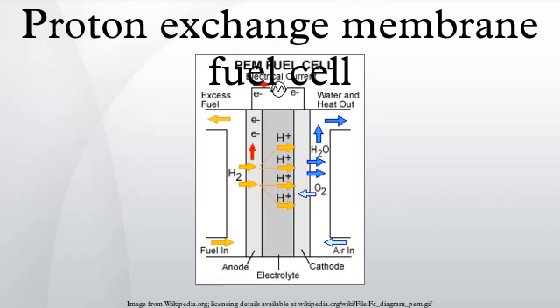Water management is a very difficult subject in PEM systems, primarily because water in the membrane is attracted toward the cathode of the cell through polarization. A wide variety of solutions for managing the water exist, including integration of electroosmotic pumps. Furthermore, the platinum catalyst on the membrane is easily poisoned by carbon monoxide, and the membrane is sensitive to things like metal ions, which can be introduced by corrosion of metallic bipolar plates, metallic components in the fuel cell system, or from contaminants in the fuel and oxidant.